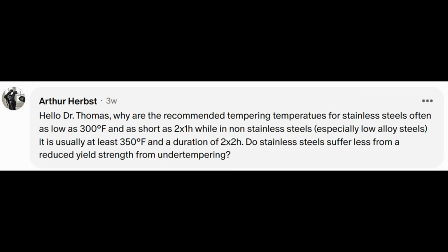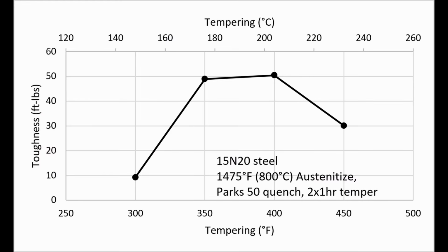And I have recommended as low as 300 degrees for low alloy steels and high alloy steels. Typically, I don't recommend any lower than 300 for anything. But there are certain steels where you need a certain minimum tempering temperature to get a big jump in toughness. One example would be 15N20, where at 350 degrees Fahrenheit tempering, we saw like 40, 50 foot-pounds, and at 300 degrees, it was much, much lower.